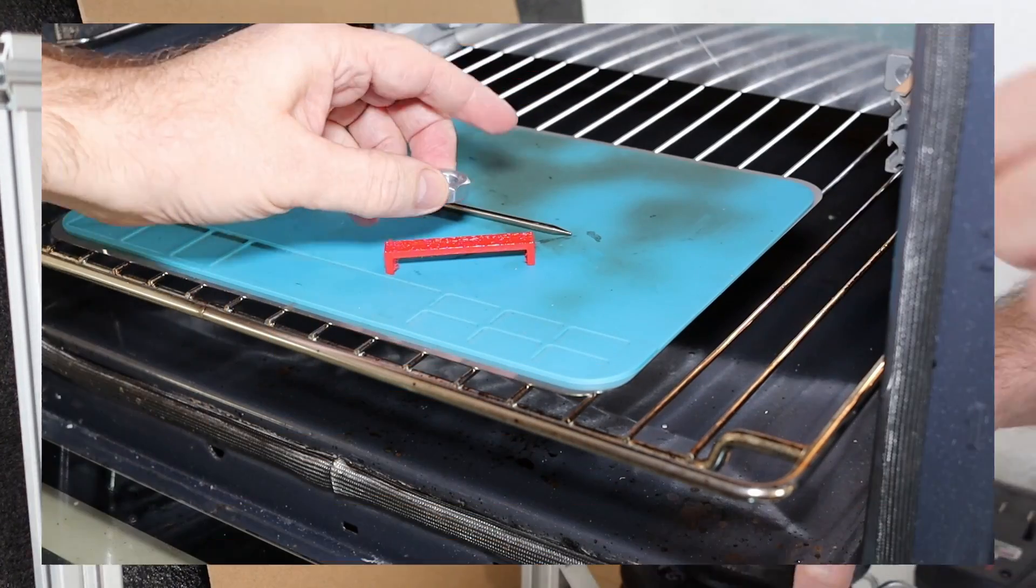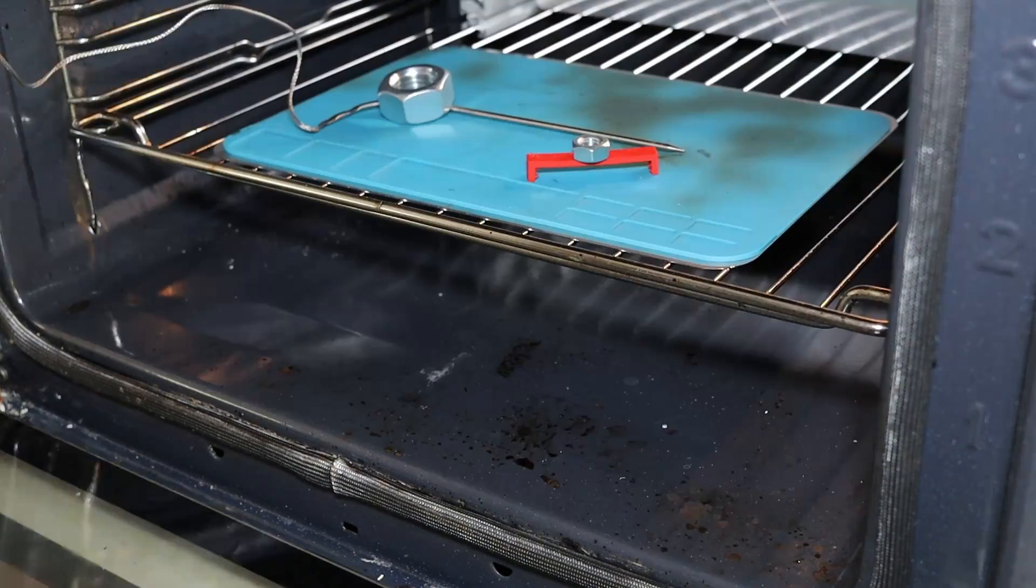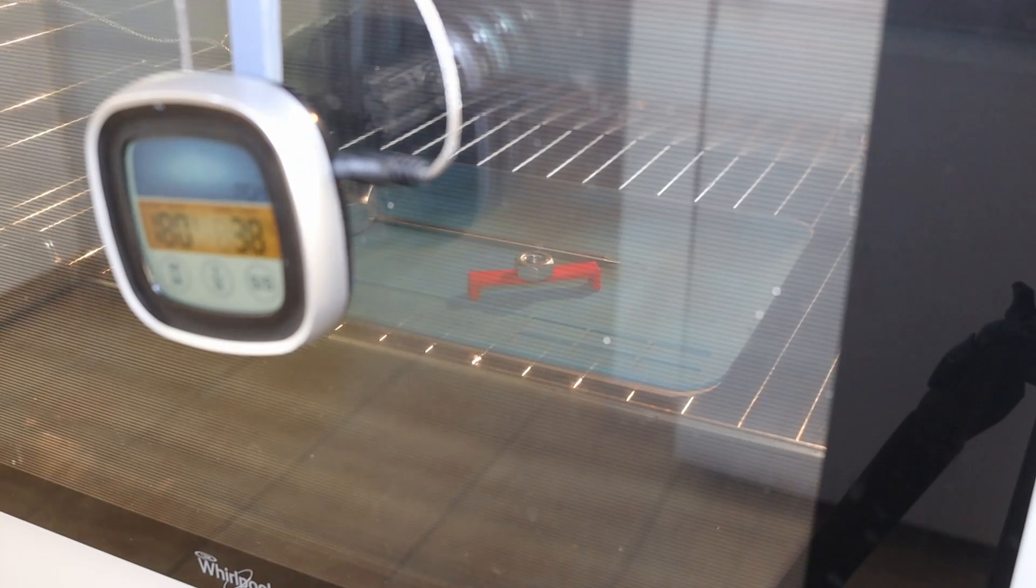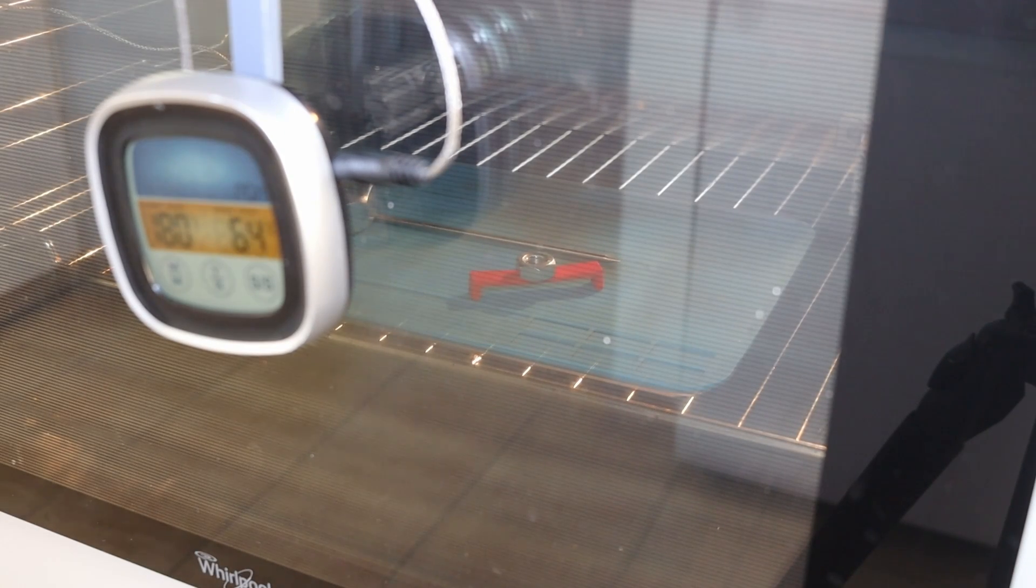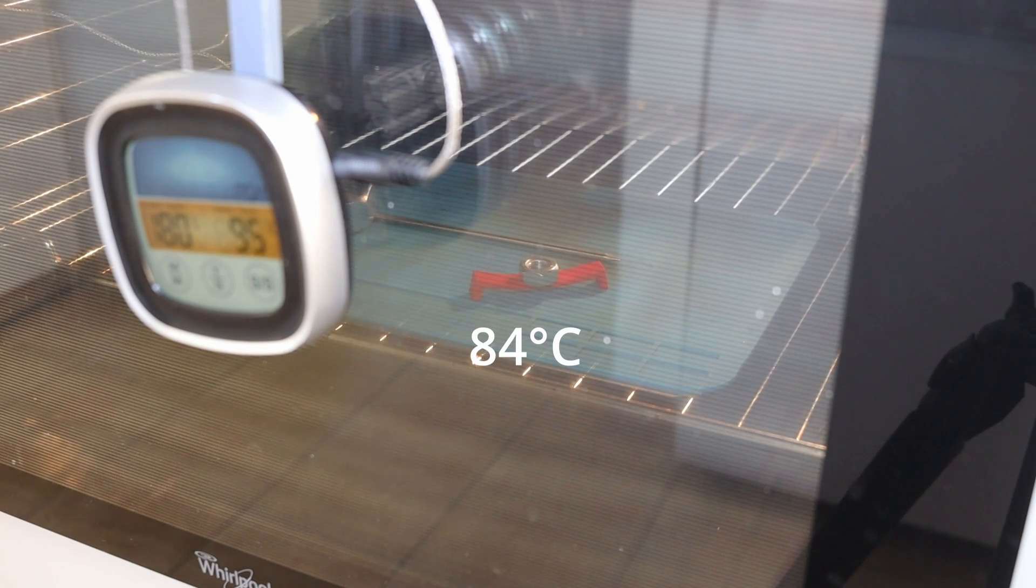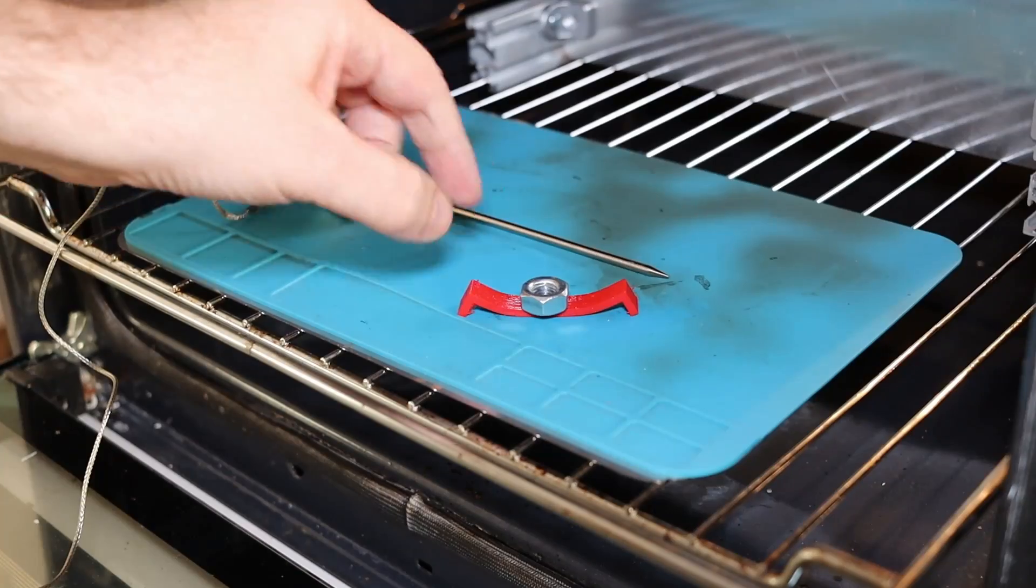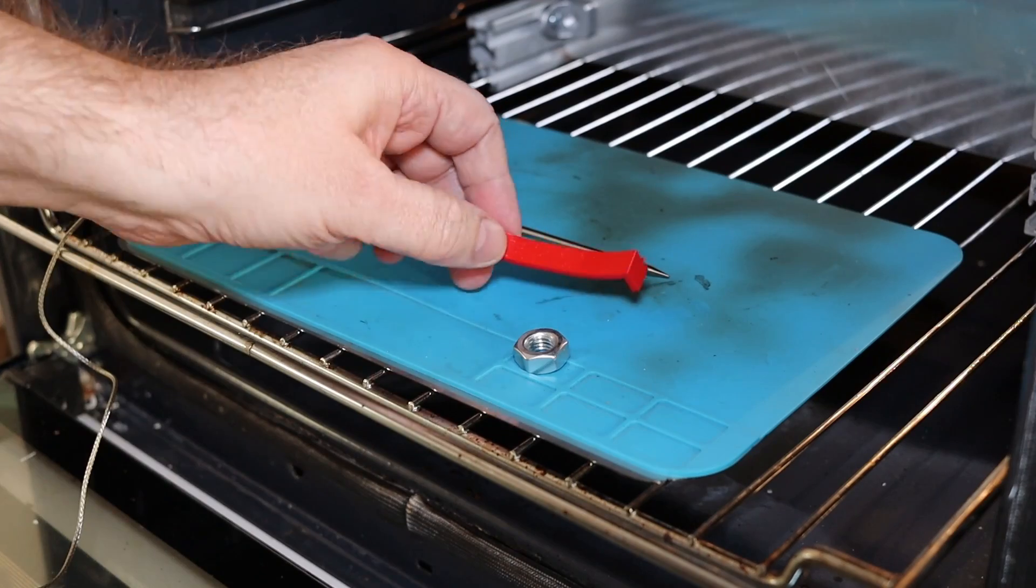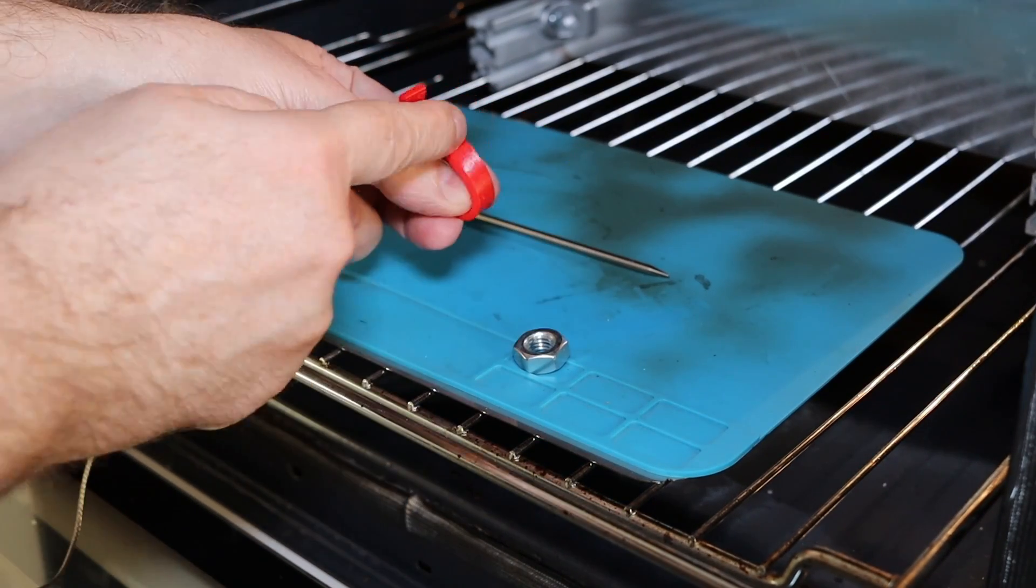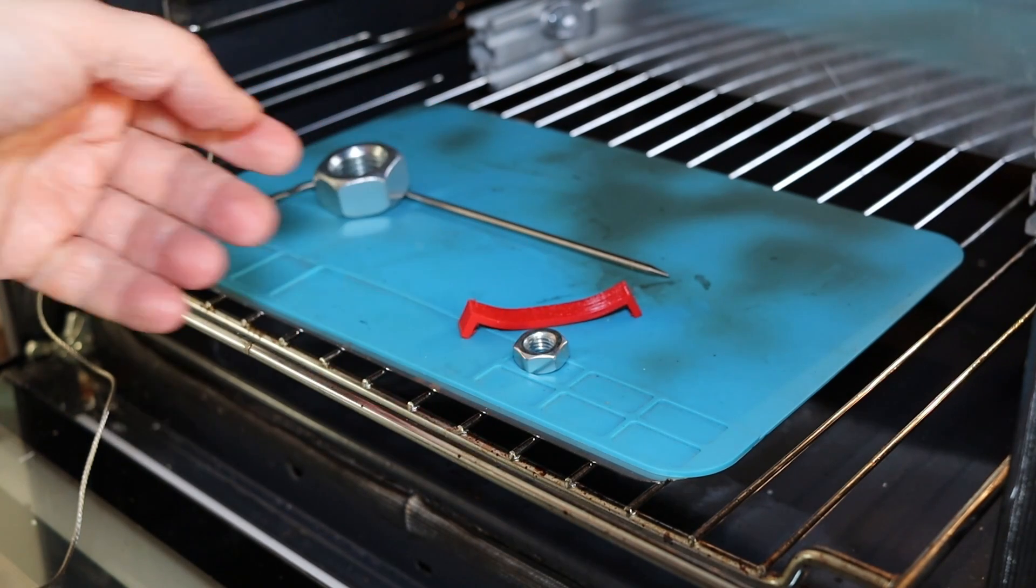The temperature test - the load is M10 nut but this is very flexible filament so it is very close to deformation but I will try to measure something. And this is sped up video, a timelapse. Notice first deformation at approximately 84 degrees celsius. I stopped the experiment at 110 degrees celsius. And actually for the feeling it has the same flexibility like before this test - I can touch it after maybe half a minute but the flexibility is very similar.